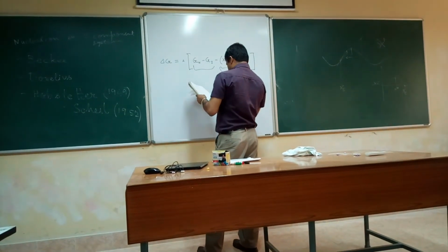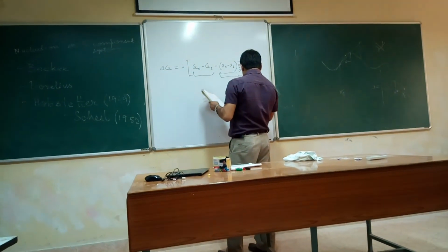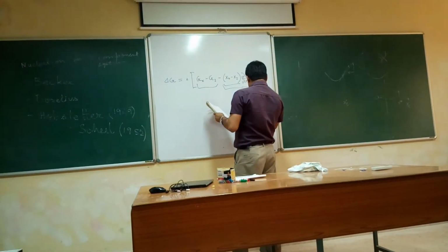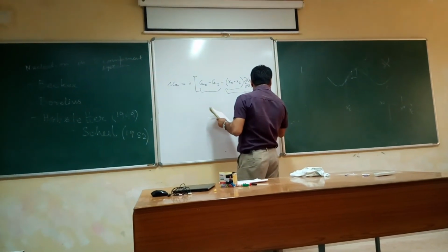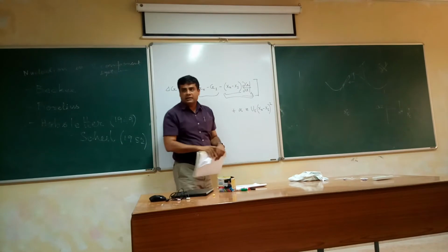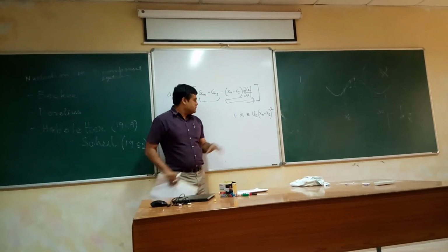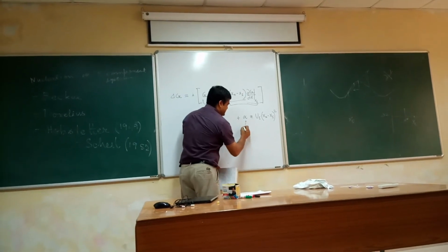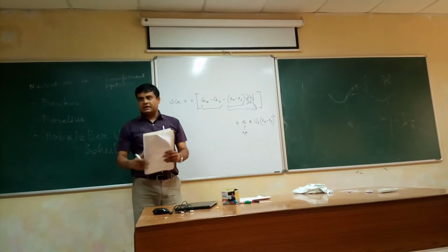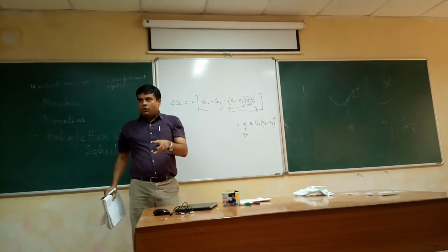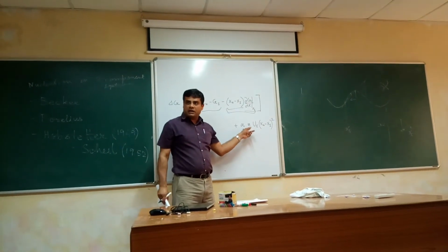And the surface energy term is alpha Z UV, Xn minus Xi whole square. Whatever Baker wrote for the surface energy term, he wrote this with that N star. So alpha takes care of the geometry, the number of atoms over the surface, and it is proportional to the coordination number.